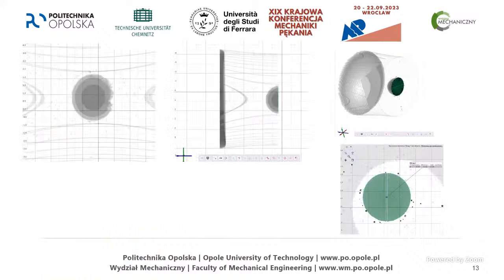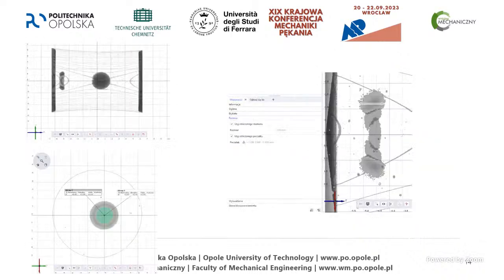If we have the scan of our void like this, nothing beside it. But in some of our specimens, we have something like an artifact, presumably something that has been maybe a computer failure or something during the printing process. Because we have also measured that area. As you can see, it's enlarged on the right side, right? It's something like a ring element, a little bit conical, like a cone being cut. In some specimens, we have this area that maybe later on can influence the fatigue tests, as we can assume.